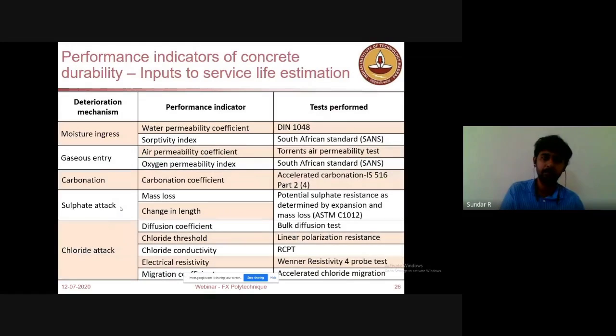Here are some of the performance indicators corresponding to the deterioration mechanism. When you have to worry about moisture ingress in a particular location, you should check the water permeability as well as sorptivity based on the available standards. Also, when gases enter, like oxygen or CO2 entering your concrete, you should have necessary specifications indicating the performance of concrete against the entry of gaseous elements like CO2 and oxygen, which is again necessary for corrosion. Similarly, for carbonation, we have an accelerated carbonation test. Similarly, for sulfate attack, mass loss and expansion could be characterized by some tests, and we will have that as a guideline for the performance of mixes against sulfate attack.